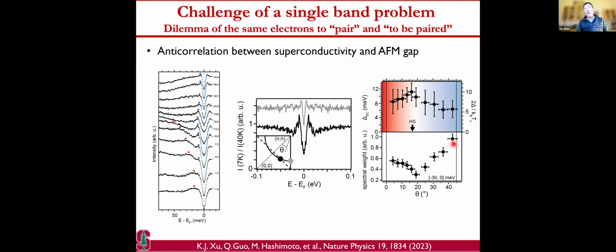So this connects to the earlier one. This is really the anti-ferromagnetic pseudogap. It broadens the feature. Okay, and yet surprisingly, in other words, it damages all the low-lying states. And you need low-lying states for superconductivity. So in that sense, the pseudogap is very bad for superconductivity. So the anti-ferromagnetism appears to be simultaneously doing bad things and also promoting good things.